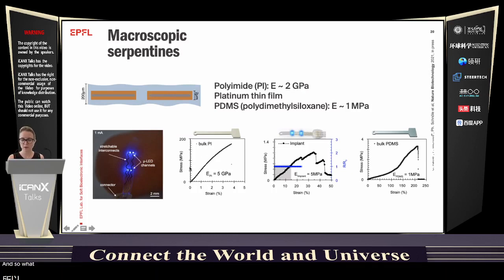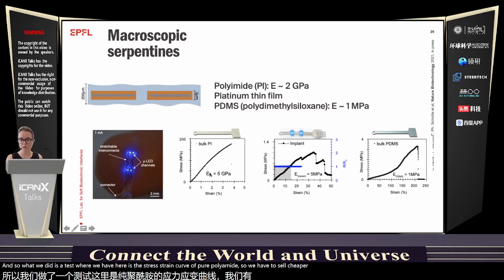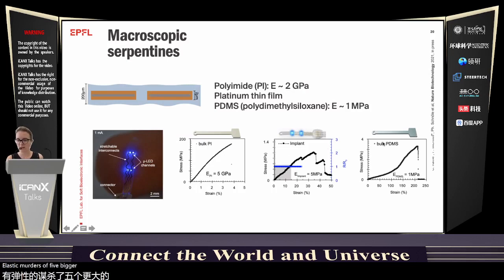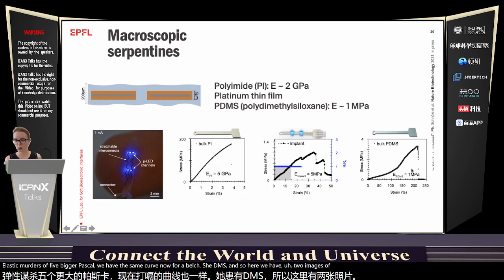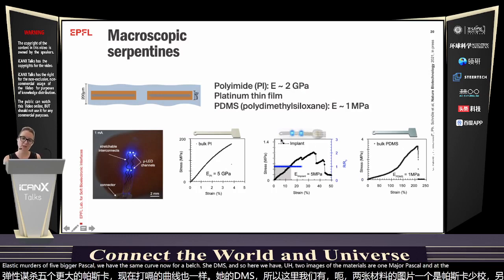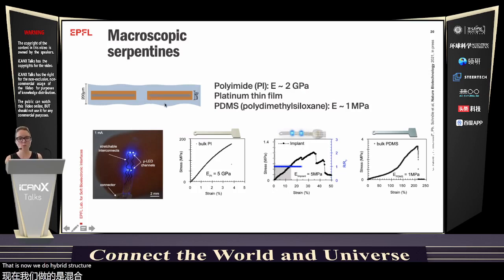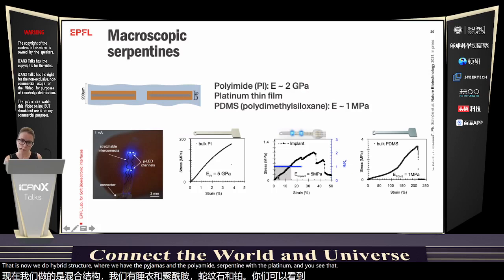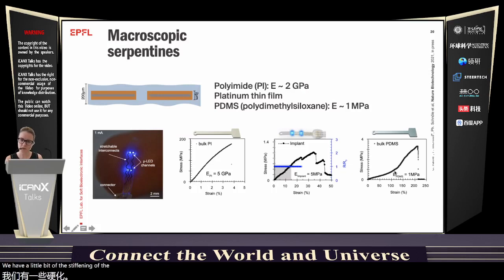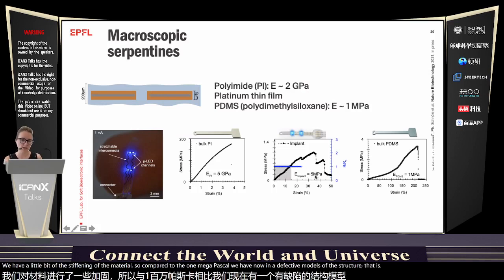And so what we did is a test where here is the stress strain curve of pure polyimide. So we have this typical elastic modulus of 5 gigapascal. We have the same curve now for bulk PDMS. And so here we're at a much softer material, 1 megapascal. And at the center, it's actually the same stress strain curve in black that is now with the hybrid structure where we have the PDMS and the polyimide serpentines with the platinum. And you see that we have a little bit of stiffening of the material. So compared to the 1 megapascal, we have now an effective modulus of the structure that is about 5 megapascal, but yet we have a structure that remains very compliant.